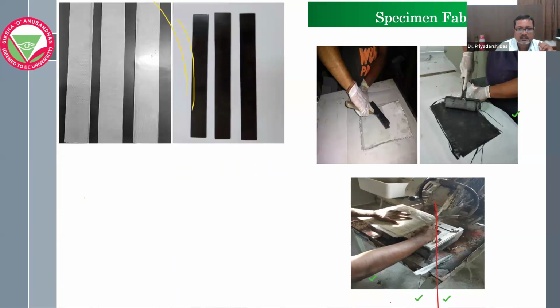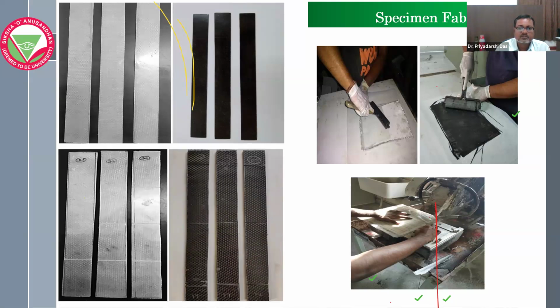These are the beams after extraction, after cutting from the diamond cutter. These are the beams in their intact stage, and these are the beams in cracked stage. That means cracks are engineered there. Through a hacksaw, cracks are engineered as per the requirement. If it is an 8-layer beam, we can engineer the cracks up to 1 layer, 2 layer, 3 layer, 4 layer, and it must be done with great precision. Otherwise, your sample will be lost.